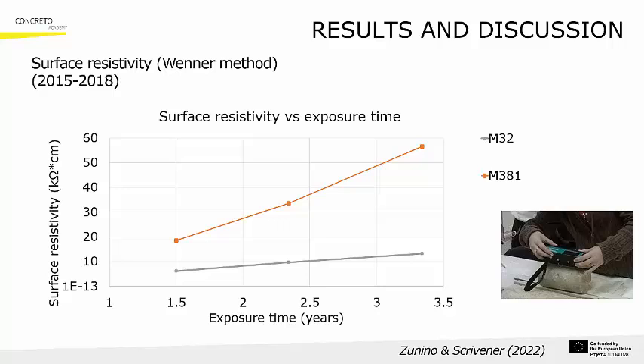Electrical resistivity is not only an indicator during the initiation period, it is also a key parameter that defines the deterioration rate during the propagation period. The kinetics of electrochemical corrosion reactions are highly dependent on the electrical resistivity of the concrete, and this will be demonstrated in the following slides.